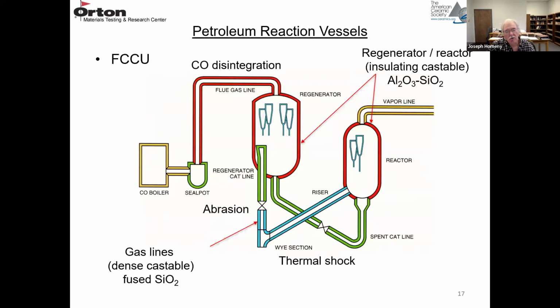So here's one of those units. Here's the reactor. Here's the regenerator. So this is where the catalyst is regenerated. There's various tubes that move the material and extract the products. The regenerator and the reactor are usually lined with an insulating castable, like an aluminum silica material. And then these different tubes are subject to abrasion and thermal shock.